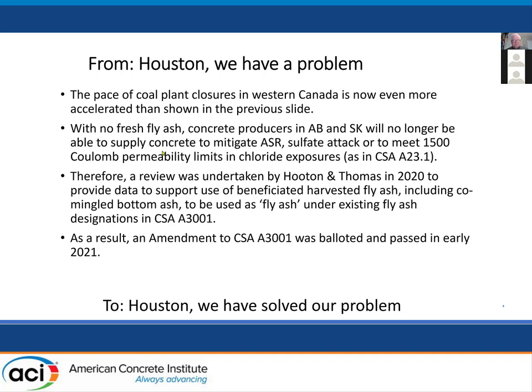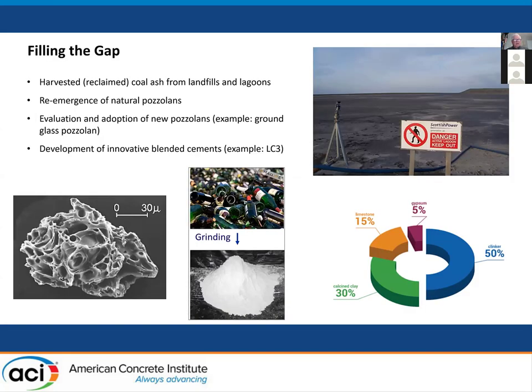And then we actually wrote a report which was presented to the Canadian Standards Committee. And as a result, we amended the Canadian Standard just about a month ago to allow the use of beneficiated harvested ash, even if it's commingled with bottom ash, and just call it fly ash, either class F or class C based on its chemistry. So we've solved our problem, at least for now. And there are plants actually starting to produce. They've set up facilities to beneficiate the ash in Alberta. So we've been filling the gap with reclaimed coal ash from landfills and lagoons.